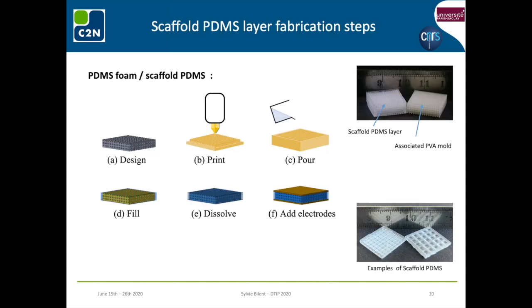The fabrication process is as follows. A sacrificial negative mold is firstly designed and fabricated using a commercial 3D filament printer. Here, the mold is fabricated in polyvinyl alcohol, PVA. The 3D printed sacrificial mold is replicated into a polymeric structure of PDMS. To ensure complete filling of the microchannels with PDMS through capillary action, the sample was maintained at rest for an hour.